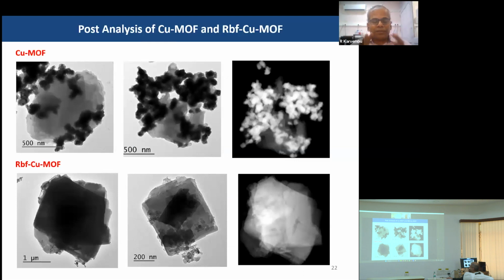Interestingly, we analyzed the used catalyst. After the experiment, we removed the catalyst and analyzed it by means of TEM. We can see the copper MOF has been converted into particles after the electrochemical experiments. The particles may be copper or copper oxide. We are still analyzing the nature of the particles by means of XRD.